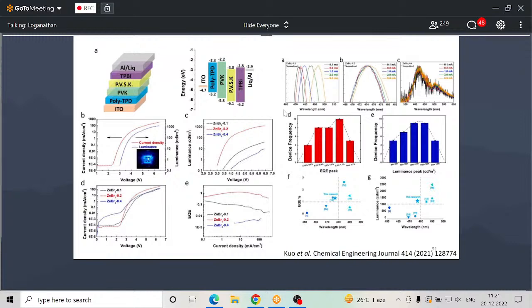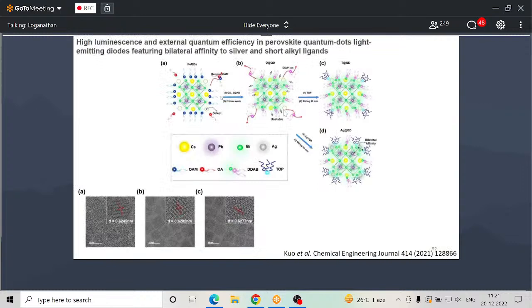And in the next project, we also do perovskite ligand optimization. In this, we try to form quantum dot structures. Here you can see the TEM image, which is around less than 5 to 10 nanometers, in that range. How can we optimize the condition? Because in the conventional system, they use some OA and OAm ligands. But in this case, we are trying to tune that kind of ligands, because ligands are going to protect your nanoparticles or your quantum dots. That kind of growth control is quite important to get good emission properties.